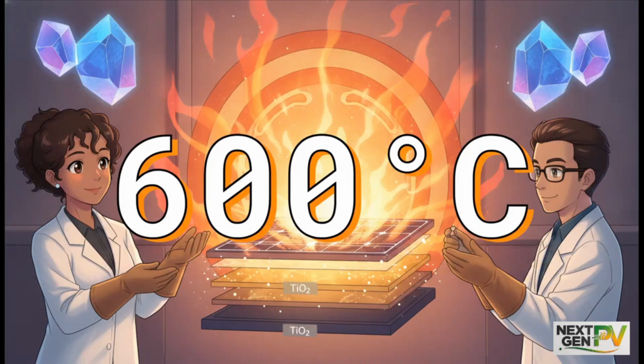Now, while ITO might look like the winner on paper, FTO is actually the most common choice in laboratory perovskite solar cells, and here is why. At 500 to 600 degrees Celsius, FTO has excellent thermal stability. You see, in solar cell manufacturing, adding layers like titanium dioxide often requires high-temperature sintering. FTO can survive this intense heat without melting or degrading, which basically makes it the rugged, dependable workhorse of the entire industry.